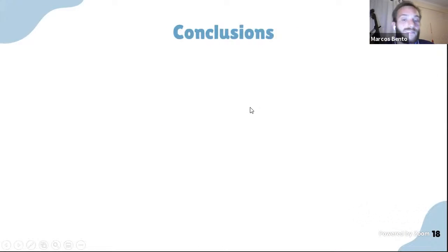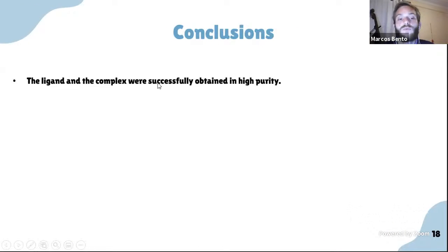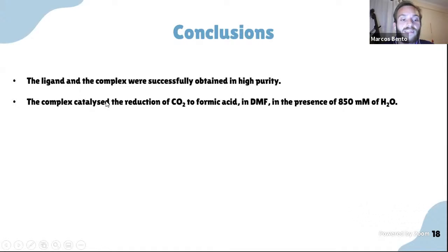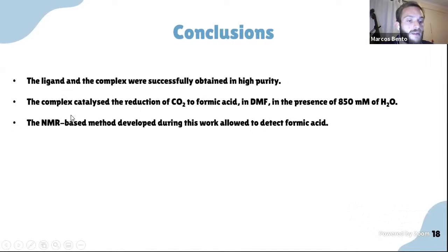So finally, we can conclude that the ligand and the complex were successfully obtained in high purity. The complex catalyzed the reduction of the carbon dioxide into formic acid in the presence of 850 millimolar of water. The NMR method used in this work allowed us to detect formic acid.